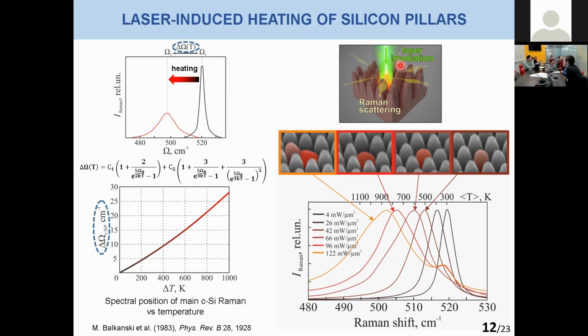It's linear with regard to the pumping intensity, but quadratic, parabolic, with regard to the field enhancement factor, which is an internal geometrical property here. So Eugene just perfectly answered.